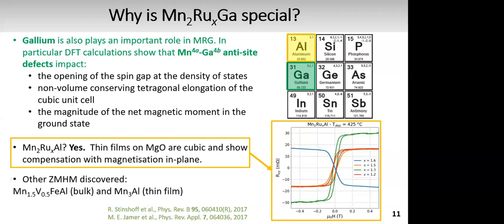And just to mention, there were other zero moment half metals discovered. One was prepared in bulk, that's manganese 1.5, vanadium 0.5, iron, aluminium, and also manganese 3 aluminium thin films grown on gallium arsenide. So once again, we see manganese in both of these compounds.